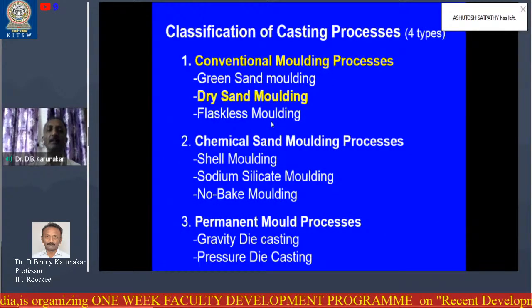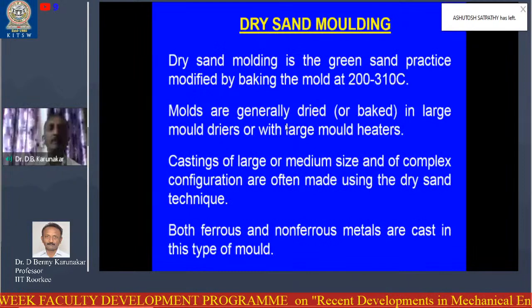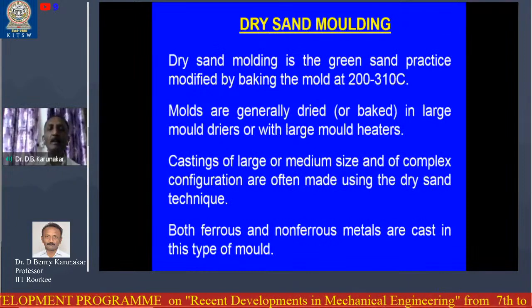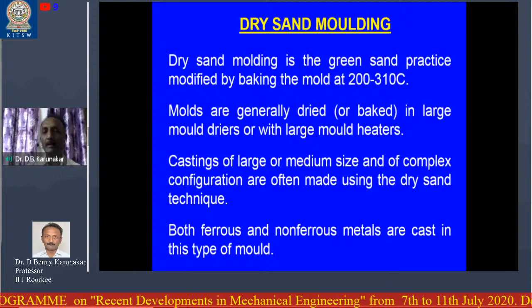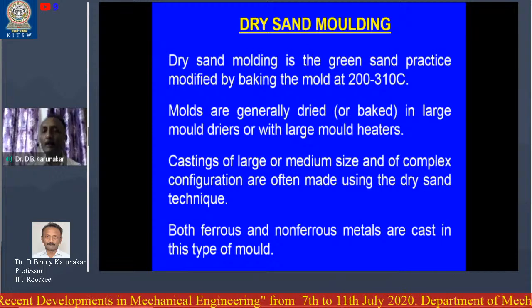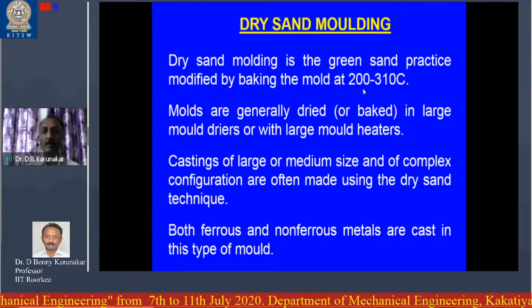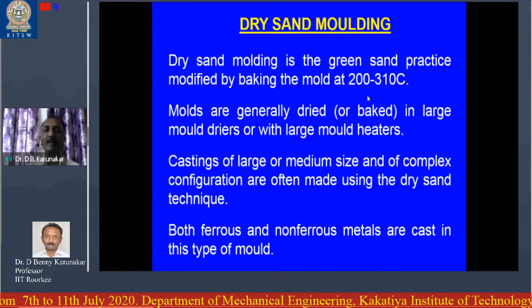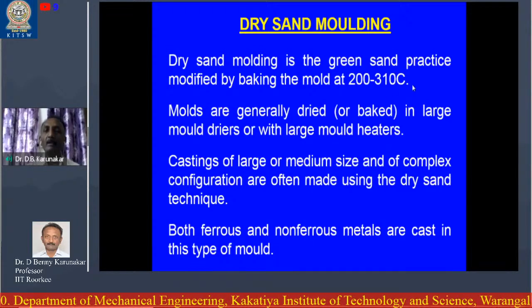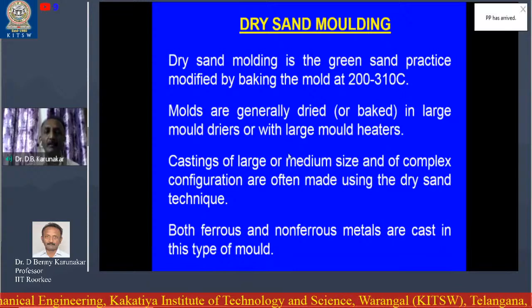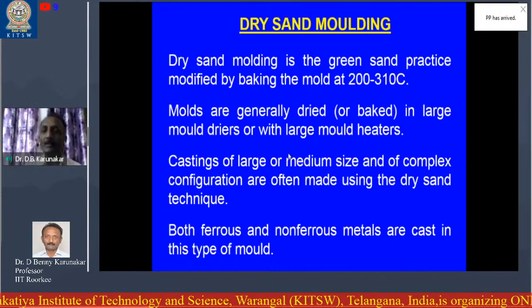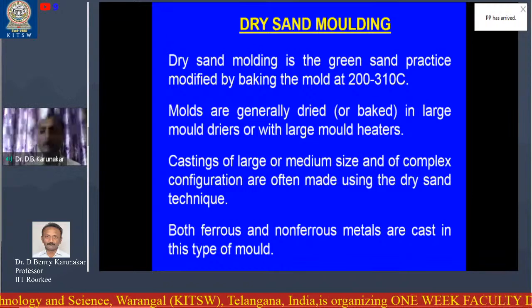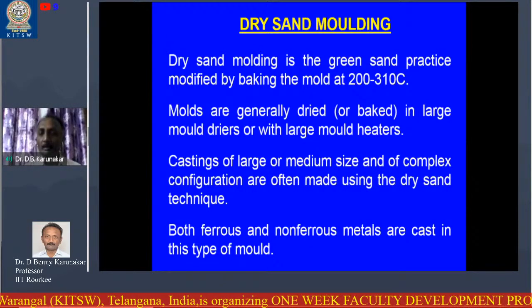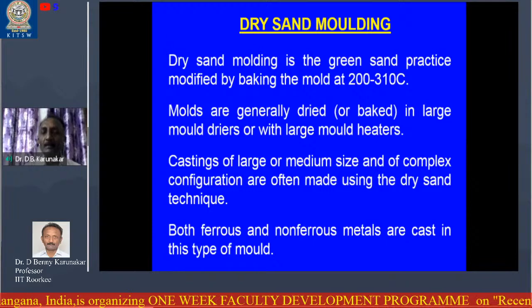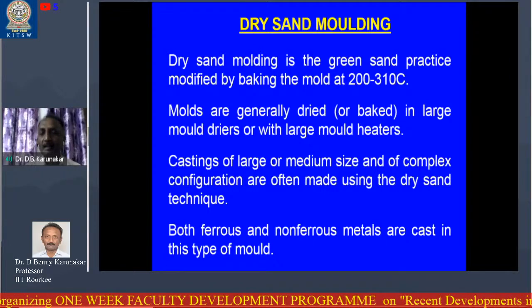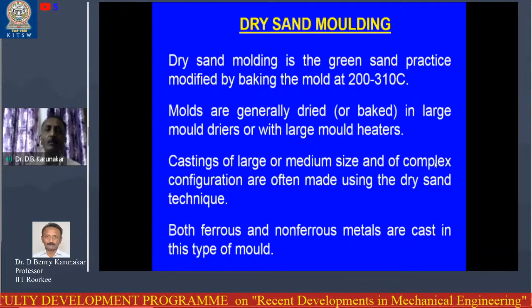Next one is dry sand molding. This dry sand molding is the green sand molding only, but it is modified in the sense that before pouring, the moisture is totally dried out. The mold is baked in an oven at about 200 to 310 degrees centigrade. The reason is the moisture in the mold may react with the molten metal and form gases and porosity defects, gas defects inside the casting. So to prevent this, we use dry sand molding.